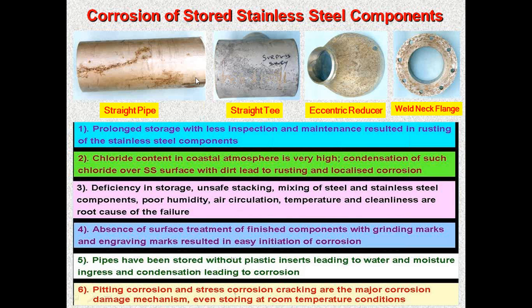And pipes were stored without any plastic inserts. Normally, both ends of the pipes should be closed with plastic inserts so that moisture does not get in and condense, and rainwater or anything else does not enter and start a corrosion problem. The main problem was pitting and stress corrosion, which was mainly due to poor storage conditions.